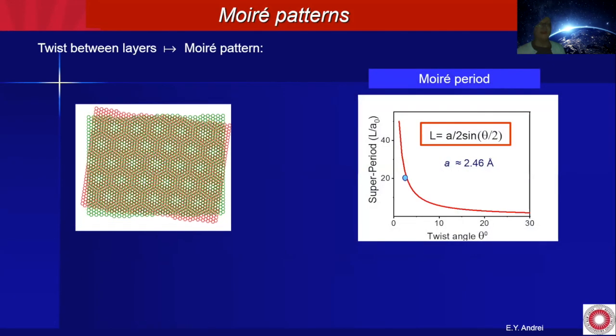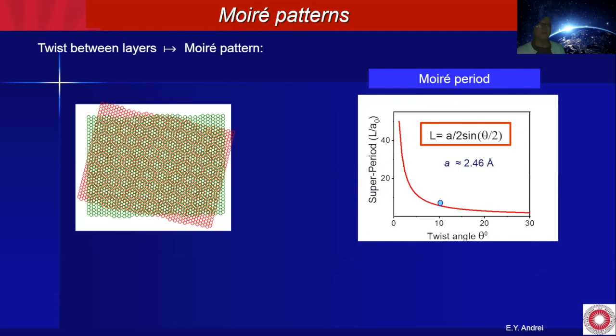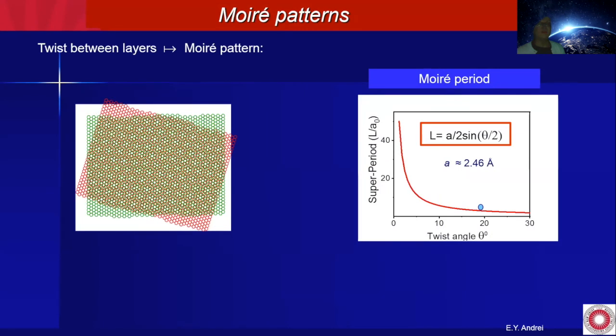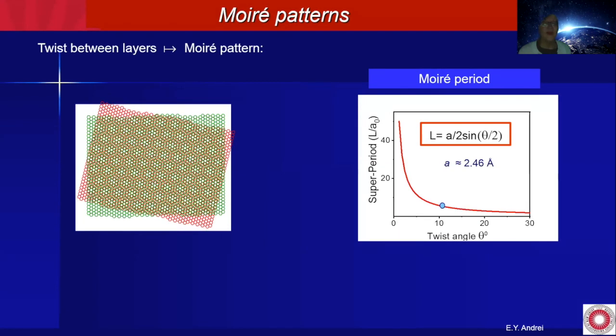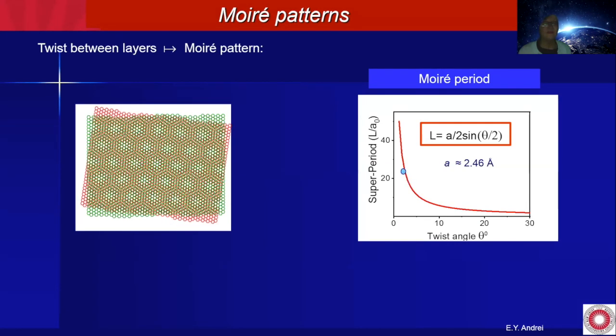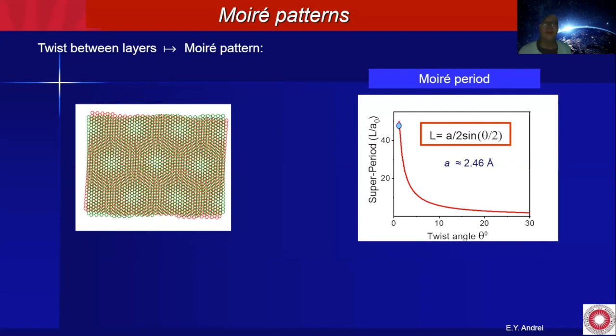So what I've done here, I've taken a layer of graphene, the green one, I put it down, and I put a red one on top and twisted it. As you twist it, you see the super period here, whose wavelength varies inversely proportional to the twist angle. Now I'm going to twist it back, and you see the pattern becomes larger and larger because the angle becomes smaller and smaller.